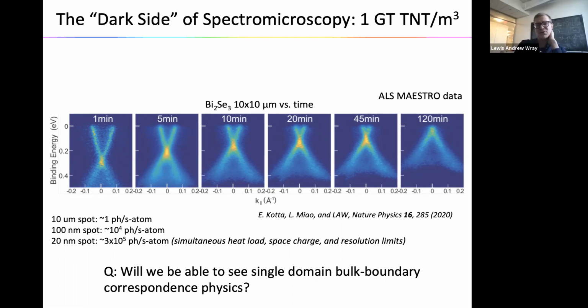If you tell the story of it, almost all of the photons are being absorbed in the top, let's call it 20 nanometers or less at these photon energies. And you get a primary electron that has order 50, 100 eV, and it quickly scatters with many other secondary electrons and shares the energy. So you get a downward cascade that is also simultaneously carrying the heat away. So locally it's very complicated.